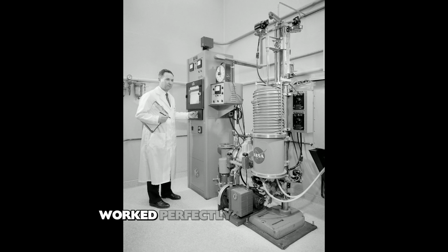Transistor radios that worked perfectly during morning operations would become unreliable by afternoon. Signal amplification would drop by 30 or 40% as temperatures climbed above 85 degrees Fahrenheit. By the time ambient temperature reached 95 degrees, common in Korean summers, the transistors were essentially useless. Soldiers reported that radios would recover functionality at night when temperatures dropped, only to fail again the next day. This wasn't battle damage or manufacturing defects. It was something intrinsic to germanium itself.